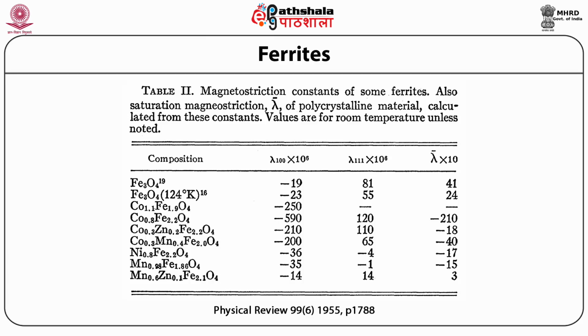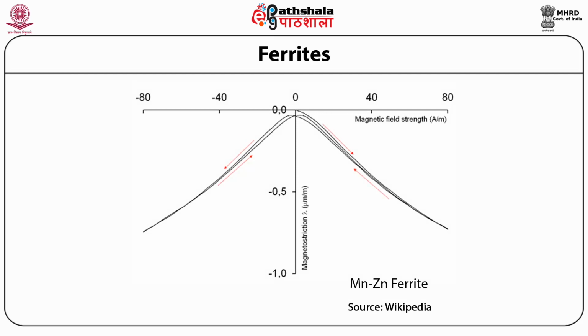As noted from the table, lambda 100 is negative for all the ferrites, whereas lambda 111 is positive for most materials, but it has a negative value for Ni0.8Fe2.2O4 and Mn0.98Fe1.86O4, and lambda bar, which is nothing but the saturation magnetostriction, is also positive and negative for these materials. As we can see from the figure, which shows a hysteresis loop, this is like a butterfly loop as observed in piezoelectric materials. This graph is shown for manganese zinc ferrite, and has been taken from Wikipedia.